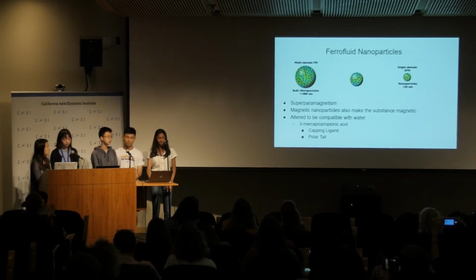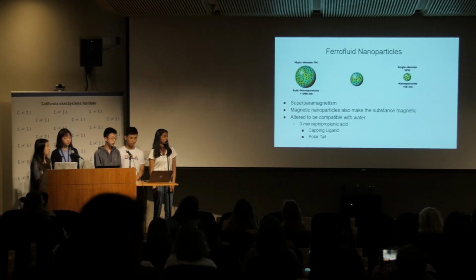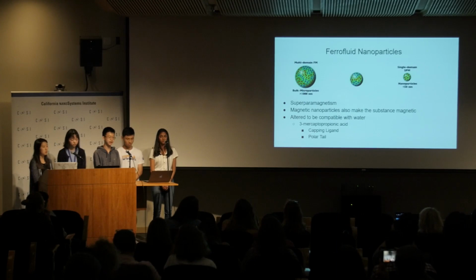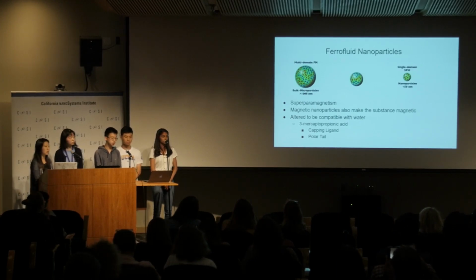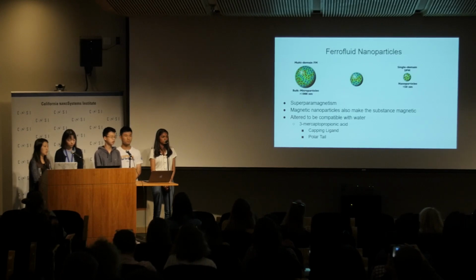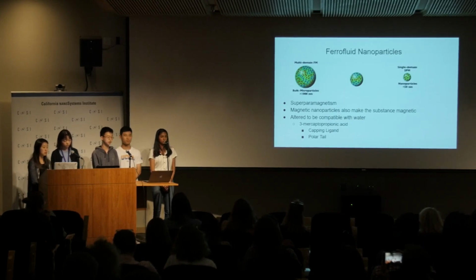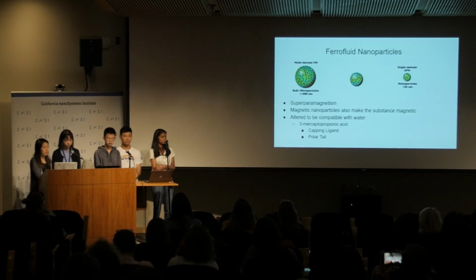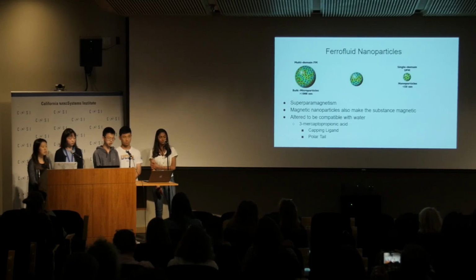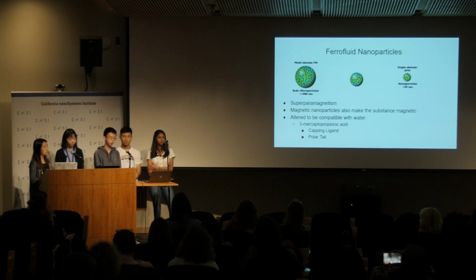To create our ferrofluid, we needed to create nanoparticles. Usually microparticles have multiple domains. Domains are areas where the magnetic fields of atoms align with each other. But as you go smaller into nanoparticles, eventually there's only one domain, which results in superparamagnetism. This makes them very responsive to a magnetic field. Magnetic nanoparticles also make the substance they're in magnetic, and we had to alter our nanoparticles to be compatible with water. We use 3-mercaptopropionic acid, which is a capping ligand we use to cover the nanoparticle, and this is a polar tail, which is able to be suspended in water.